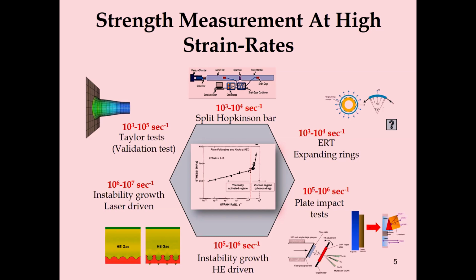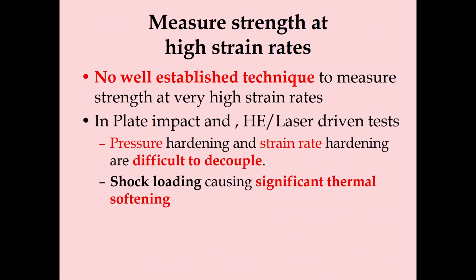But one of the problems we have, especially when we want to reach the very high strain rates, is that we're getting these coupling effects, as I described earlier. So just to summarize before we move further, none of these experiments are actually a well-established technique, besides the Hopkinson bar, of course, which is very well studied and used. All of the other techniques, when we want to reach the higher regime above 10 to the 4, 10 to the 5, we don't have a well-established technique. And as I said, we're getting the coupling effects with the existing setups.